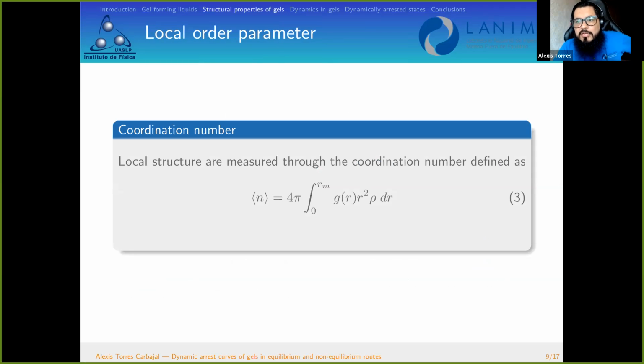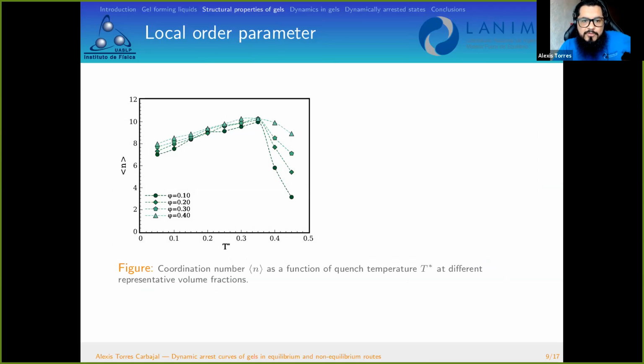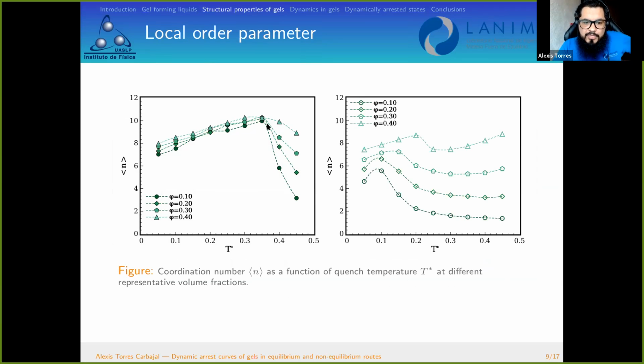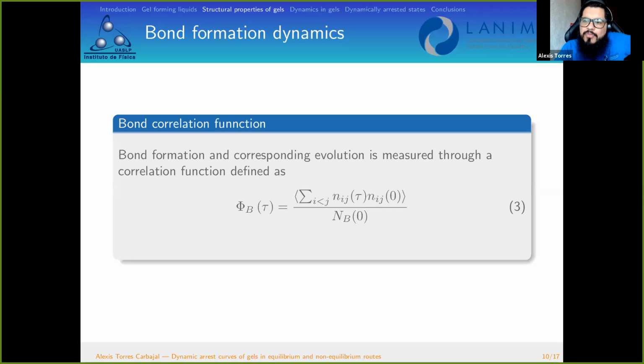So we also determine the local order parameter in order to see what the microstructure of this fluid is, and we observe an interesting feature: the Lennard-Jones fluid changes dramatically its behavior at a certain temperature, in this case 0.35. The Lennard-Jones Yukawa also exhibits such dramatic behavior, but it is dependent on the thermodynamic states. For instance, this change takes place at lower temperature if the density is lower, and as the density is increased, the threshold temperature where this change occurs is changed. So we can observe a difference between the Lennard-Jones and the Lennard-Jones Yukawa tail at the microscopic level.